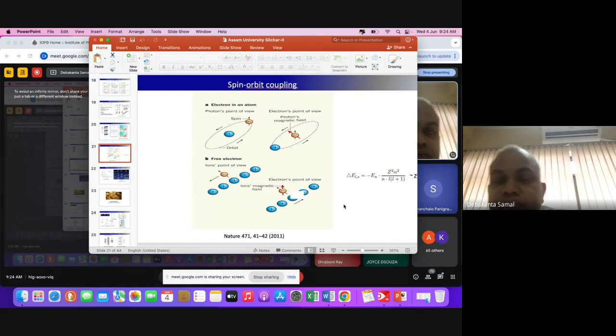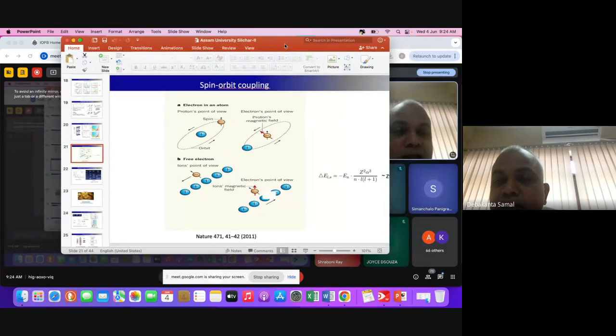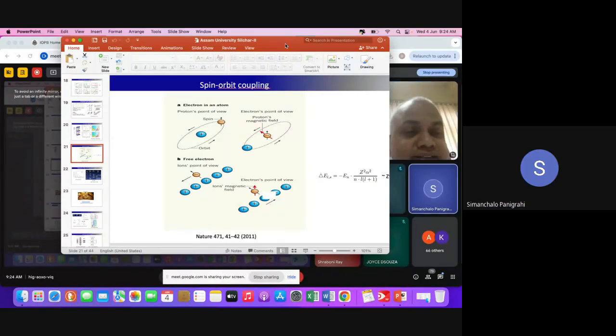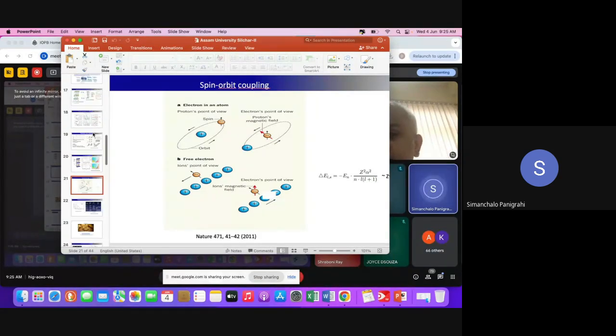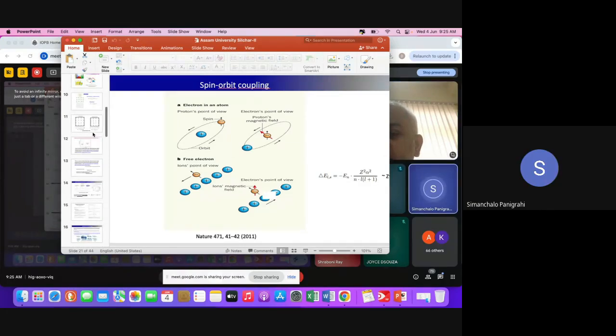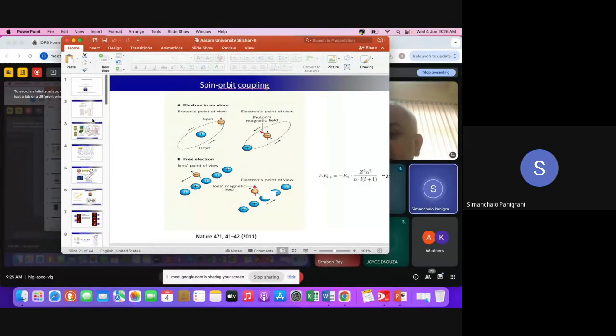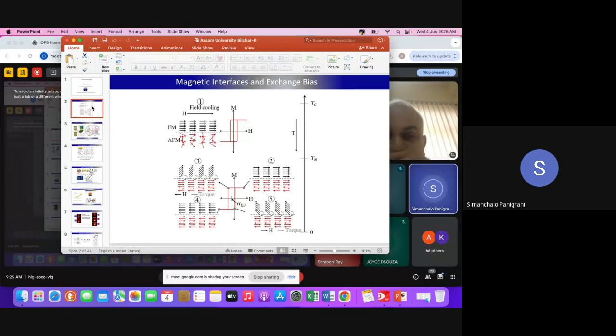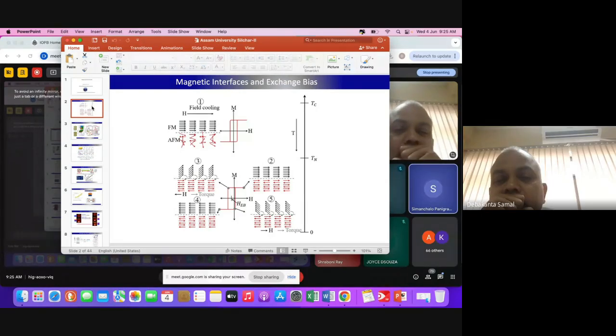Am I audible? As you are telling, when there is a ferromagnetic 2D layer over an antiferromagnetic one, and we apply the reverse bias, the antiferro will influence the ferro. But why not the reverse? Because ferro has a strong J value compared to antiferro. So why does the antiferro influence the ferro to follow the field direction, thereby leading to distorted hysteresis? Why not the reverse?